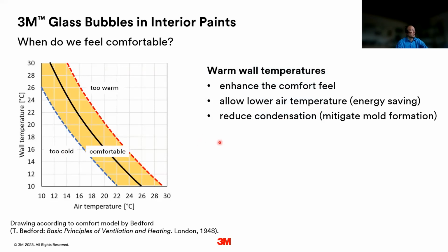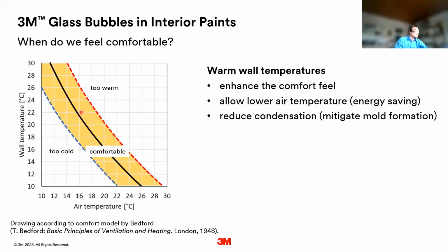And why is that important? It's about comfort. More than 70 years ago, Bedford published a so-called comfort model, where he talked about a relationship between the wall temperature and the air temperature, and where most people feel comfortable. That's this area, which is marked yellow. Let's say we have a wall temperature of 16 degrees C, then we need like 20 degrees C in the room to feel comfortable. If we can increase the wall temperature, for instance, with such a paint, then we feel comfortable also at lower air temperatures.